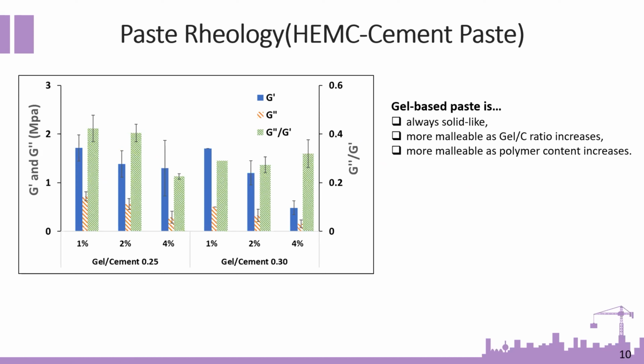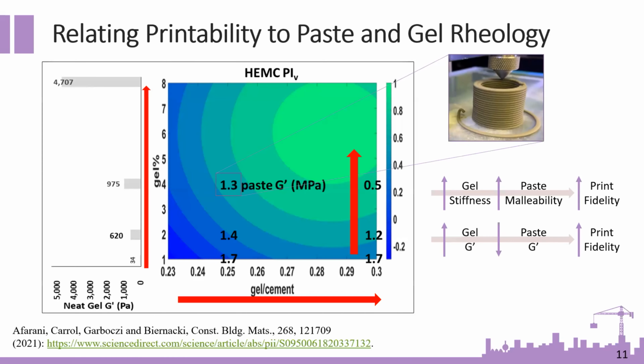I plotted here 2 different gel to cement ratios at 3 different gel percents. Here you can see that as we increase the gel percent, the paste storage modulus decreases, which is the reverse of the relationship of the gel storage modulus. So we wanted to correlate these results to the printability outcomes.